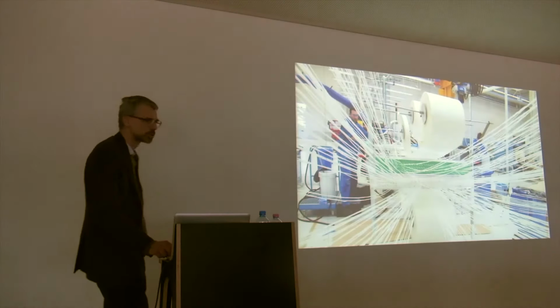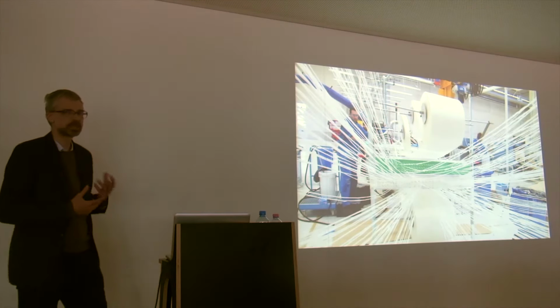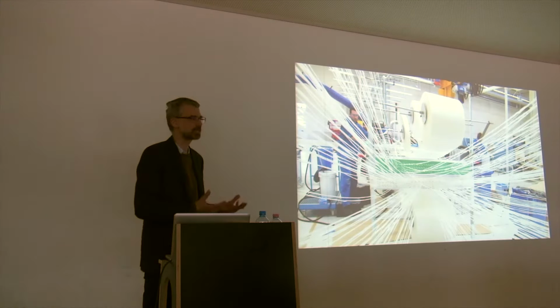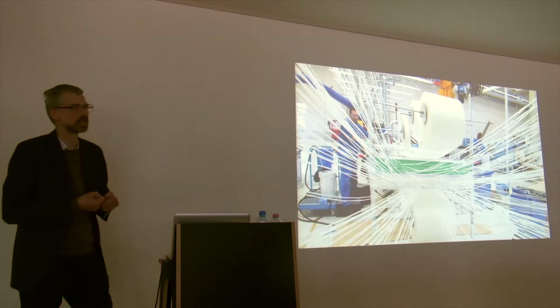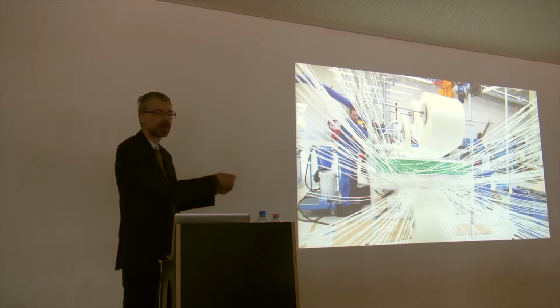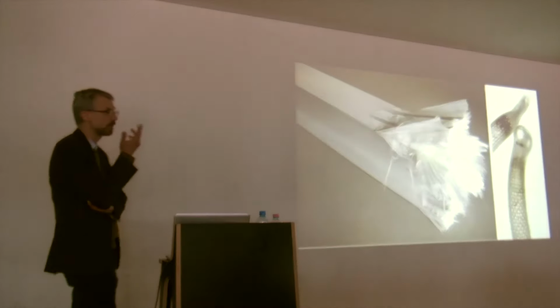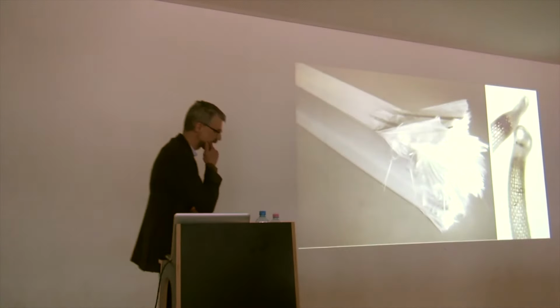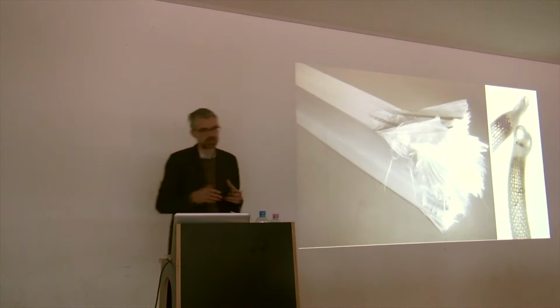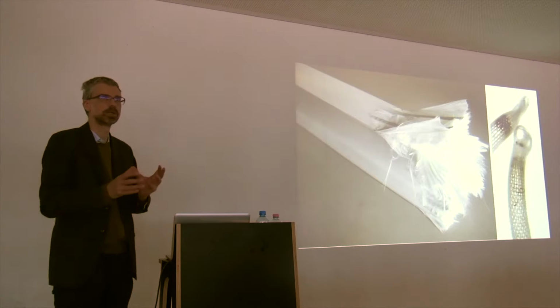Now we look at pultrusions. Pultrusions are made in a much more automated way, similar to an extrusion of aluminium which you push through a die. A pultrusion, as you would guess from the name, you pull through a die, and you wet the fibers with the polymer, and you can shape it into profiles, just like any profile, basically. Making sure that the glass fibers that you use are really placed where you need them. So you can engineer your components, you can engineer your mechanical properties from component to component, which makes it very interesting.